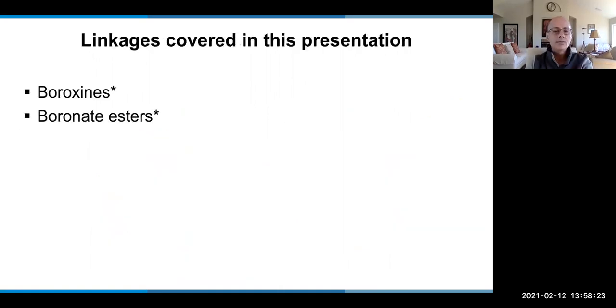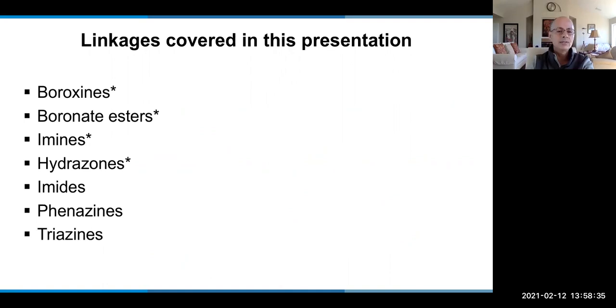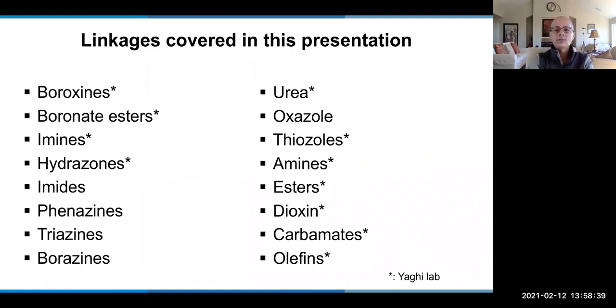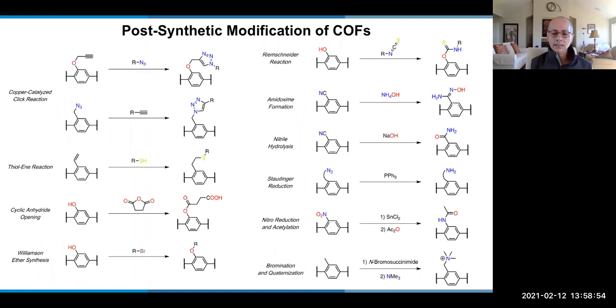And this is a summary of some of the linkages that we've done and that I've covered here: boroxines, boronate esters, imines, hydrazones, imides, phenazines, triazines, borazines, urea, oxazole, thiazole, amines, esters, dioxin, carbamates, olefins. So a lot of the very important linkages in organic chemistry are represented here. Since the backbone is very stable, you can do many organic reactions on the COF once it is formed, and still preserve the crystallinity of the structure. And this gives you a very nice handle into functionalizing the pores with many different types of functionalities.